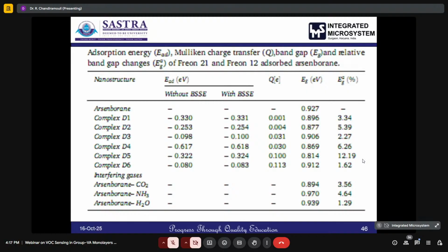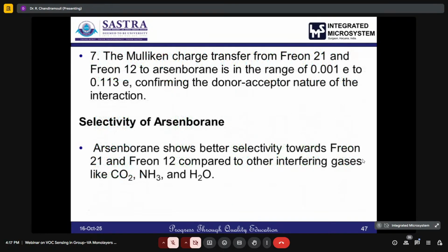The other important thing is that we have also studied the selectivity, since in the air atmosphere CO2, O2, NH3, and humidity H2O are also present. So we studied the selectivity of Freon 12 and Freon 21 along with some of the atmospheric gases. For selectivity, the Mulliken charge transfer for Freon 21 and Freon 12 is in the range of 0.001 e to 0.113 e, confirming the donor-acceptor nature of the interaction, and the selectivity of arsenborane with the atmospheric gas molecules is also reported.